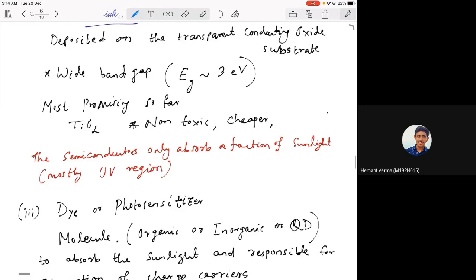And typically what you expect is that the semiconductor material should absorb only a fraction of sunlight, mostly in the UV region, because you want the absorption to happen in your dye molecule. The dye molecule absorption spectra should be such that it absorbs as many photons as it can. Therefore, you need this wide band gap semiconductor, typically with a band gap higher than 3 electron volt. For titanium dioxide, depending on the structure, it can be 3 electron volt or 3.2, something in between. So you need a little bit higher band gap so that most of the photoelectron generation happens in your dye molecule.